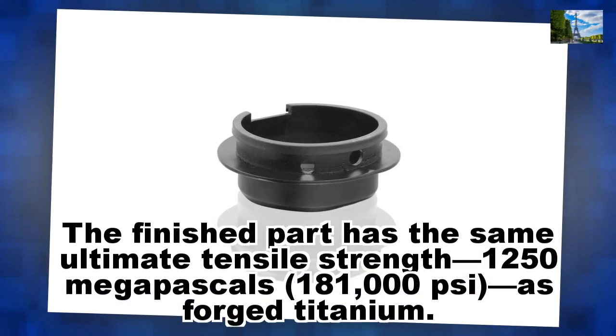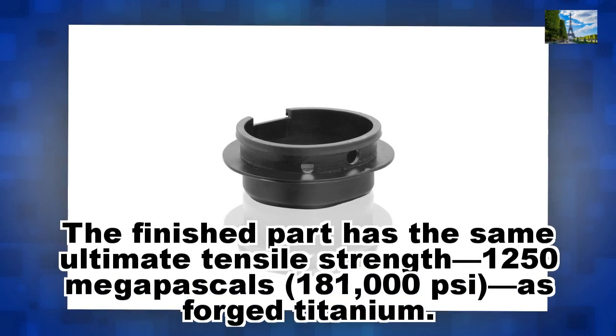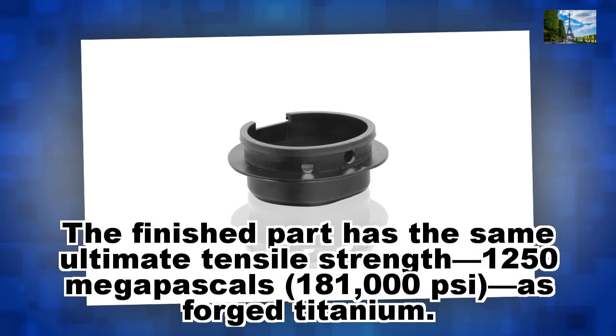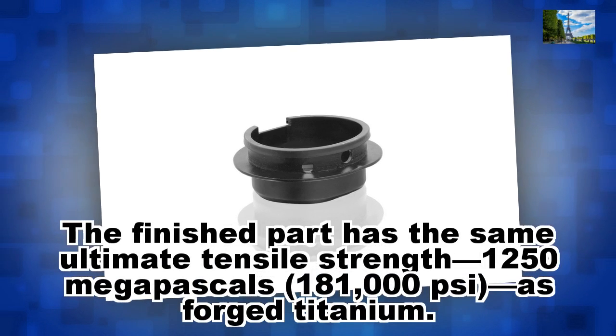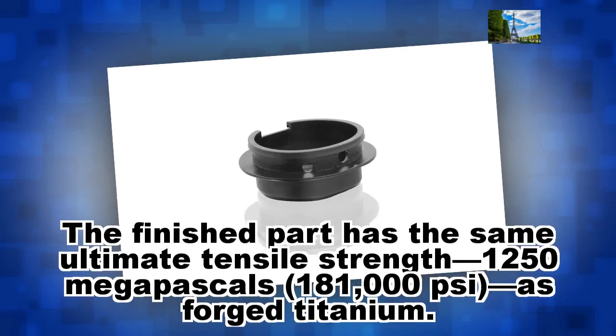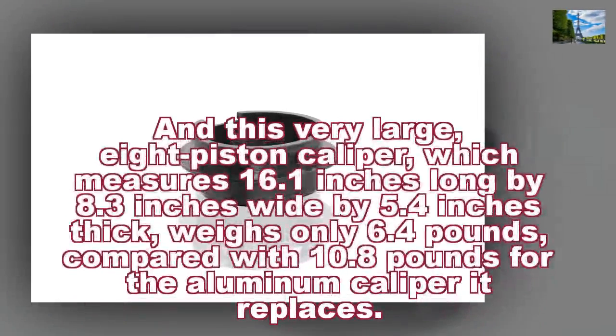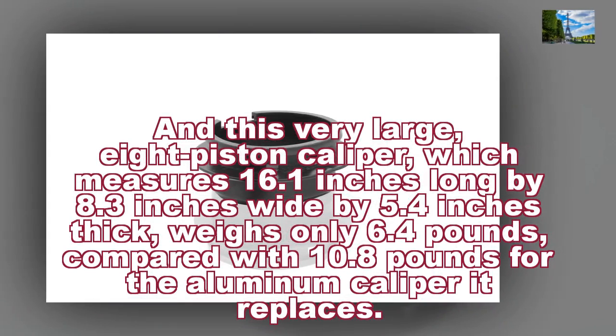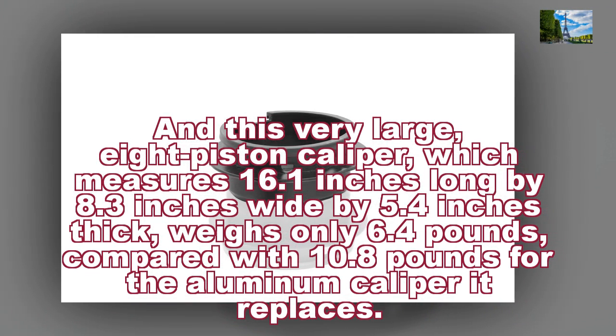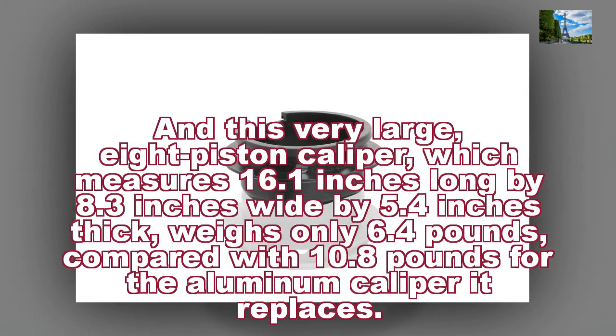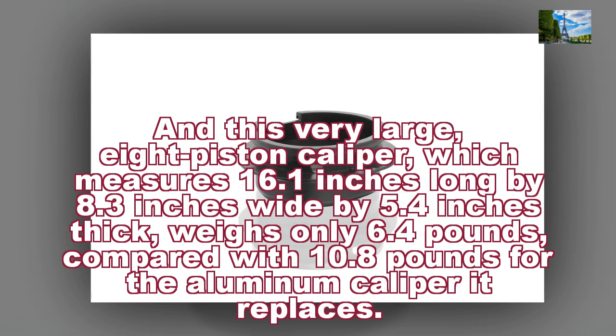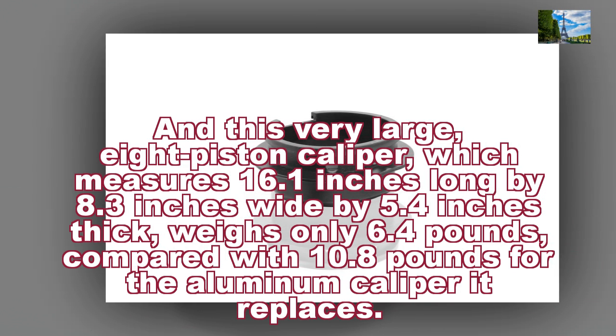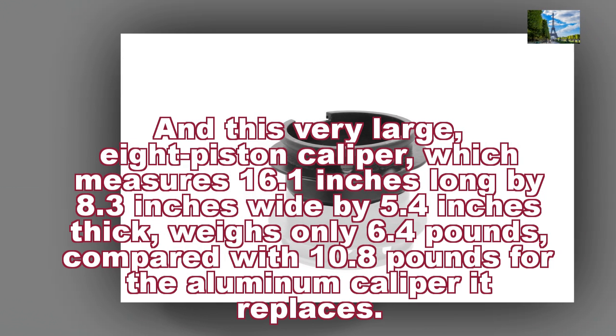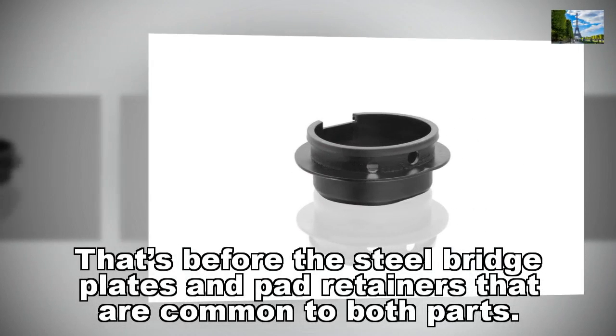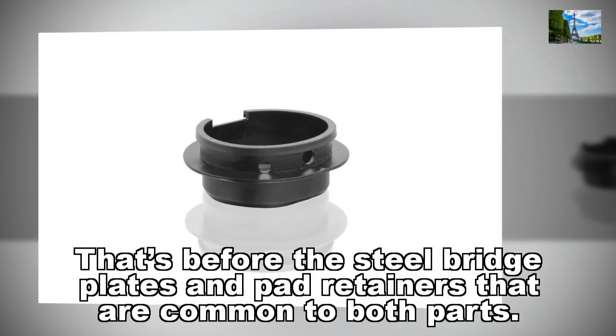The finished part has the same ultimate tensile strength, 1,250 megapascals, 181,000 pounds per square inch, as forged titanium. And this very large, 8-piston caliper, which measures 16.1 inches long by 8.3 inches wide by 5.4 inches thick, weighs only 6.4 pounds, compared with 10.8 pounds for the aluminum caliper it replaces. That's before the steel bridge plates and pad retainers that are common to both parts.